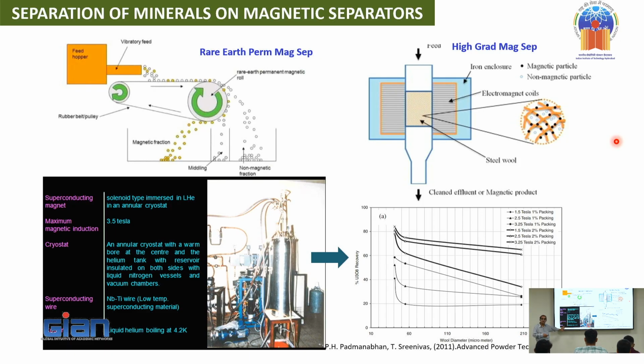Similarly, this can be used in removing some of the nuclear effluents. Nuclear effluents, after use in the reactor, do contain ultra-fine size particles, which are very detrimental if they are released to the environment. So in such cases also, these superconducting magnets are used, which are helpful in removal of those particulate matter. But there is quite a good success in the use of these high gradient magnetic separators in industry also.